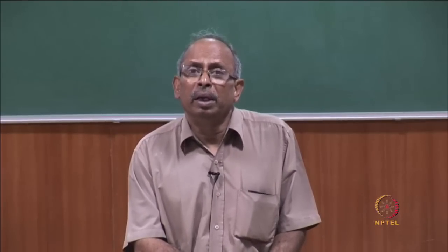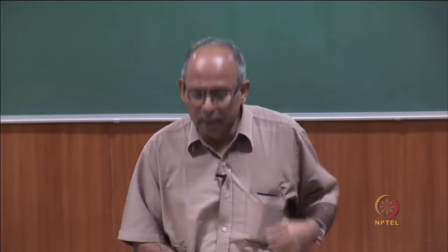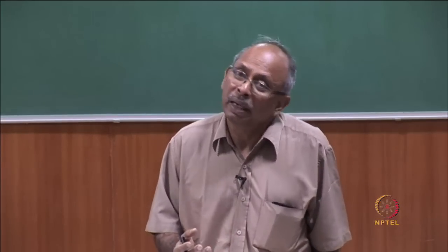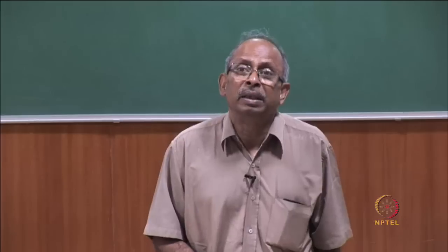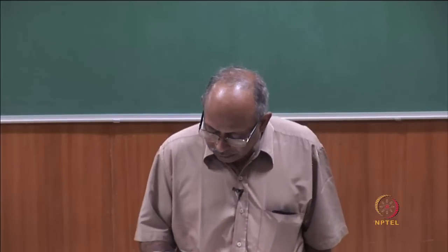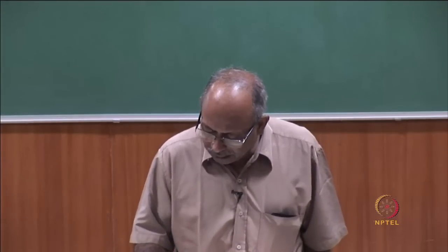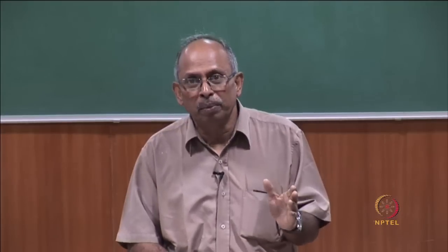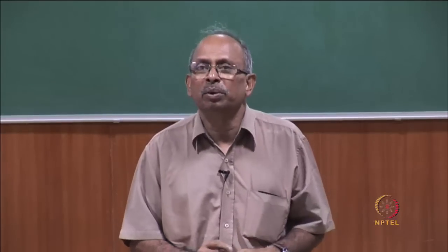So, therefore, you can only use it in limited quantity, but it is used in an engineered way so that its advantages are realized in full. The paste strength increases in this manner, but the concrete strength increases significantly. Now, why does concrete strength increase significantly? Because concrete strength is governed by the interfacial transition zone, and the interfacial transition zone improves.